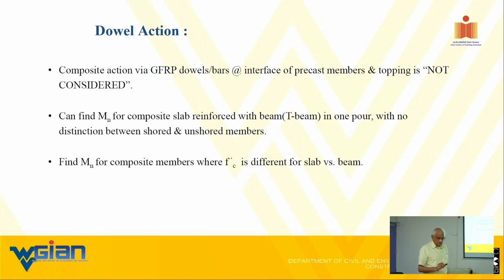So first of all, I want you to understand the dowel action, shear transfer: the ability for the FRP to resist shear by itself. Forget about the contributions coming from concrete. But by FRP only, that is neglected. As you know, the shear stress to failure in steel is about 40 KSI for a 60 KSI steel, roughly, whereas in an FRP, it's only 5 KSI. So it's not really contributing a whole lot.